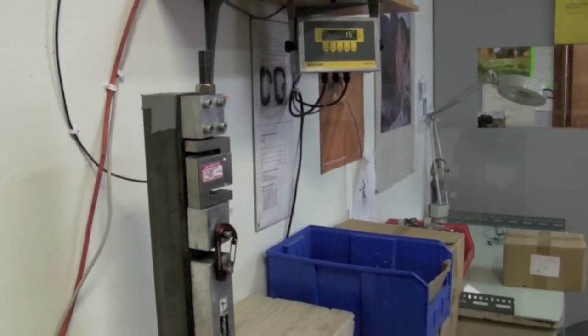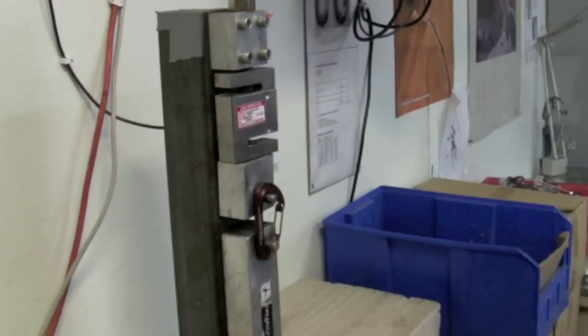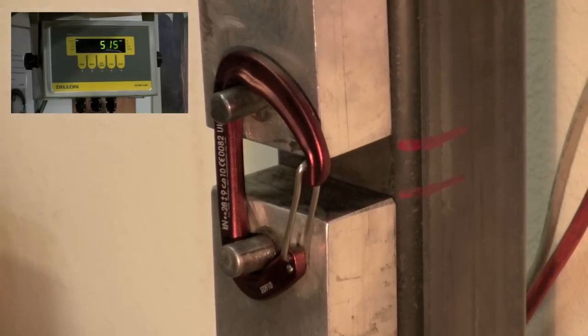Every individual carabiner is loaded to a pre-calculated load level that is based on the design and the material yield calculation unique for each carabiner type.